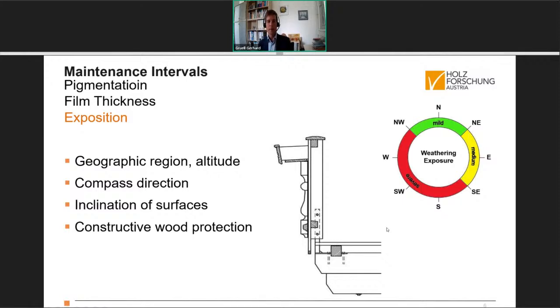And the third very important factor is exposition. Exposure conditions, you might say. How much is the surface exposed to weathering? And there are a few factors influencing this. This is the geographic region and the altitude, the compass direction, and there we drafted this nice colored compass here, and this is valid for the Central European region, where we draft our brochures and recommendations for. In Central Europe, you can say roughly that the main weather direction is from west and southwest, and that's why the conditions are severe in this part of the compass direction.